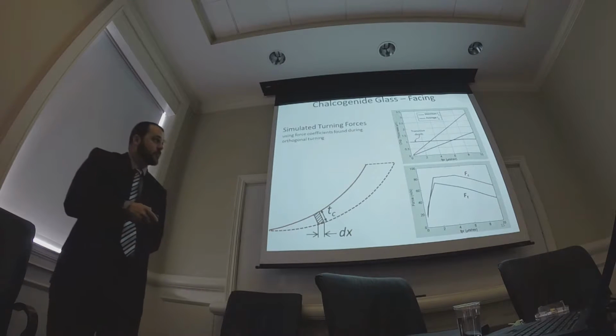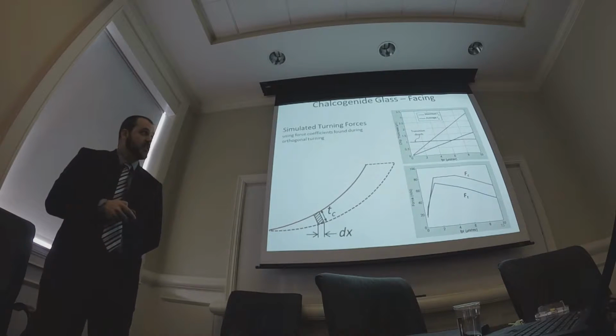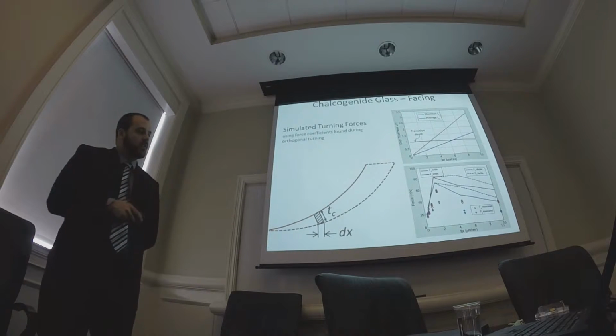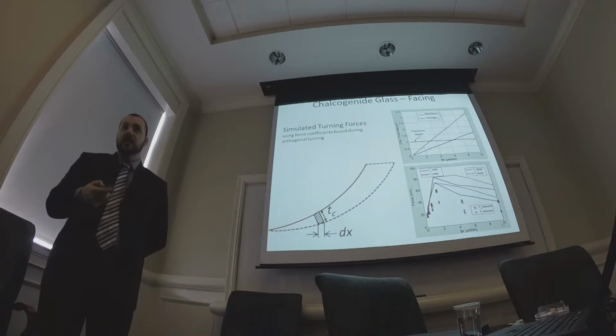We start to see it drop like we were expecting. When we compare it to the facing results, we see that there's a bigger drop from 2 to 5 than predicted by our orthogonal cutting model. So this is when I had gone back and found that hysteresis.